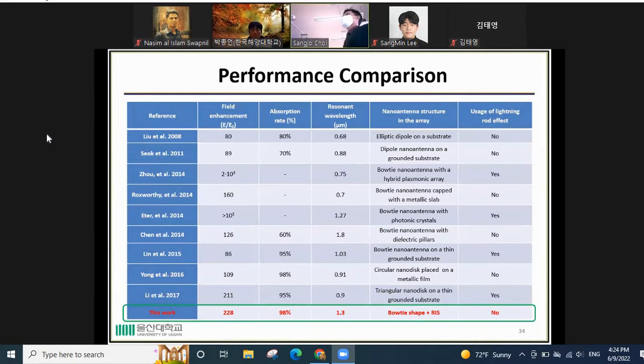And this is the performance comparison in terms of the electric field enhancement and absorption rate between our structure and other reported structures. So we see our structure showing a higher field enhancement with almost perfect absorption without using the lightning rod effect on the sharp tip of the structure.